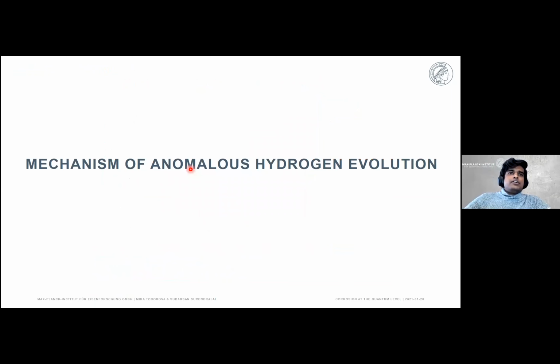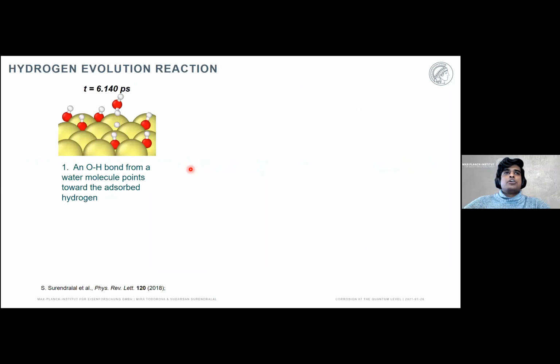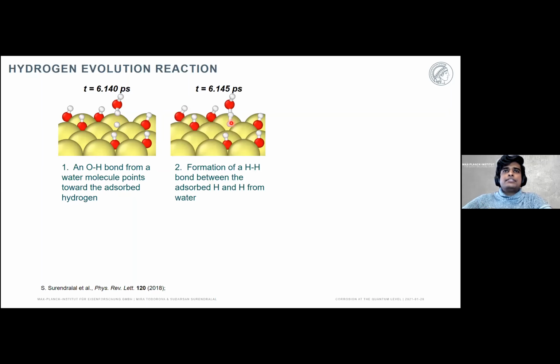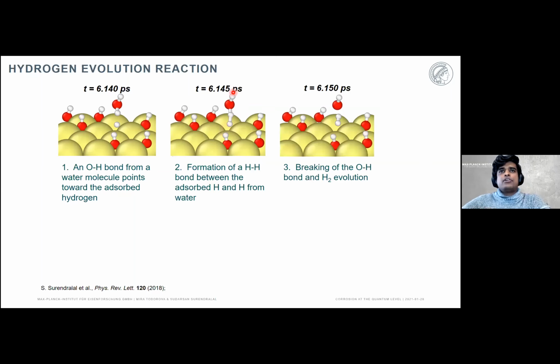So the advantage of such DFT-MD calculations is that we could actually go to the very snapshots where these reactions happen and see how the atoms move, and to understand the mechanism of such a reaction. So we take into account one such reaction that happens at about 6.14 picoseconds, and we just look at what happens at the surface. Here you can see the surface of magnesium, where we have a certain coverage of OH ions adsorbed on the surface and a single hydrogen adsorbate which is on the surface. What we see is that a water molecule approaches the surface, and one of the oxygen-hydrogen bonds is pointing in such a way that it points towards the adsorbed hydrogen. What happens then is that this hydrogen from the water is actually able to attach itself to the adsorbed hydrogen. And what happens later on is that the OH bond is broken, and then you get OH in solution and the evolution of hydrogen.